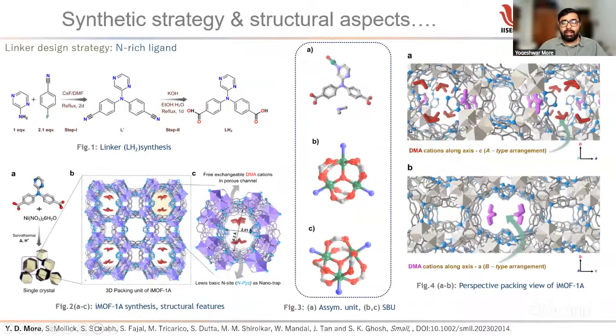So going further, since we wanted to extract the uranium, we need to have a kind of MOF which is stable, which is reusable, and which has a geometry which is pore selective, meaning it should be very selective for the uranium. Why is it so? Because we are going to extract the uranium from seawater, and seawater already has 2+ cations, which can compete with the uranium extraction.